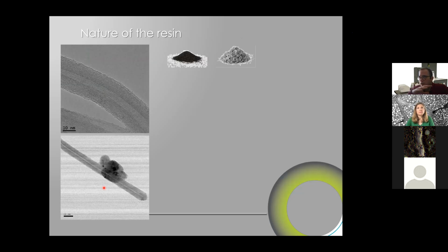So I know that some labs did some tests to load existing resin with conductive agents. Here I showed you some carbon nanotubes or some carbon black or some silver flakes and things like that. That was one of the ideas. And one of the first things we realized is that even if you take so-called carbon nanotubes, indeed they're nano, but if you look at this image and the scale bar here, you would realize that this carbon nanotube will never, ever go through the plasma membrane of a cell, simply because that's way too big. And so it cannot diffuse inside the cell.